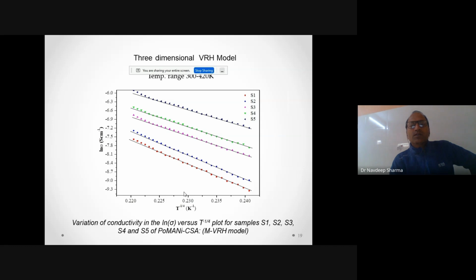So it means that in case of the Arrhenius model, the conductivity range is found to be 350 to 430 Kelvin, but in case of one-dimensional variable range hopping, the temperature range is 300 to 370 Kelvin, in two-dimensional 300 to 380 Kelvin, and in three-dimensional it is found to be 300 to 420 Kelvin.